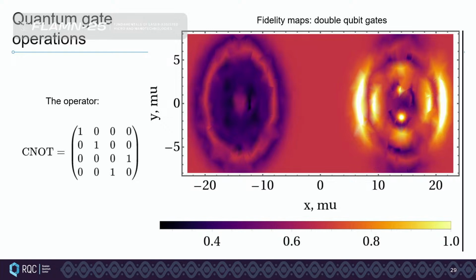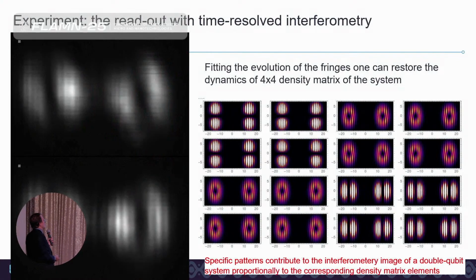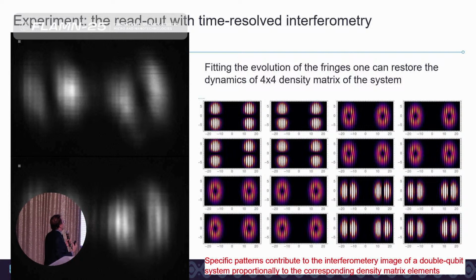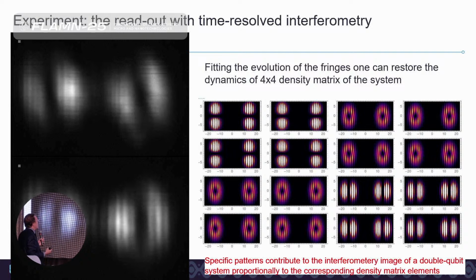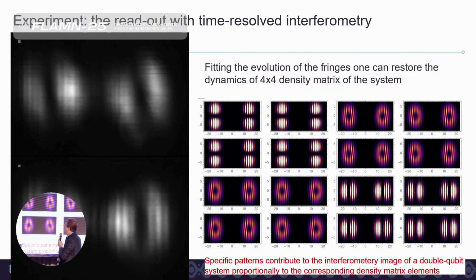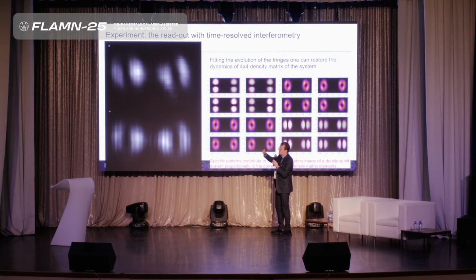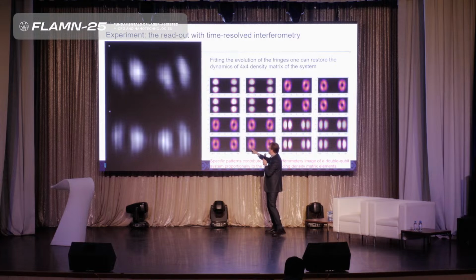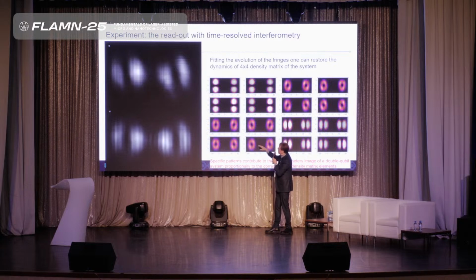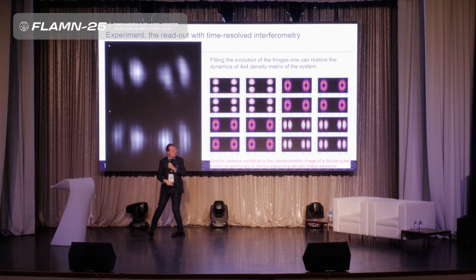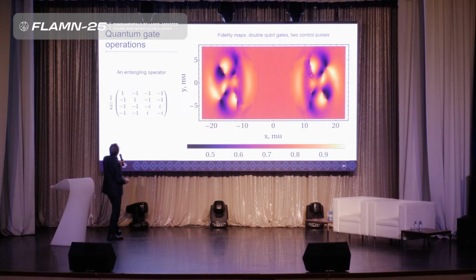We do theoretical modeling to predict the fidelity of gates like CNOT, iSWAP, and others, and then we implement it experimentally. The important issue here is readout of the state of the system, because we need to detect simultaneously in our experiment 16 elements of this 4 by 4 density matrix that characterizes two qubits. This can be done by time-resolved interferometry, where the interferometric images, which change in time, are fitted on the basis of 16 interferometric images corresponding to 16 elements of the density matrix. So this technique allowed us to attempt to demonstrate a quantum entanglement of two polariton qubits.